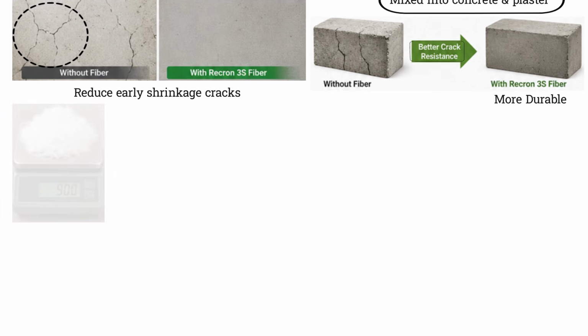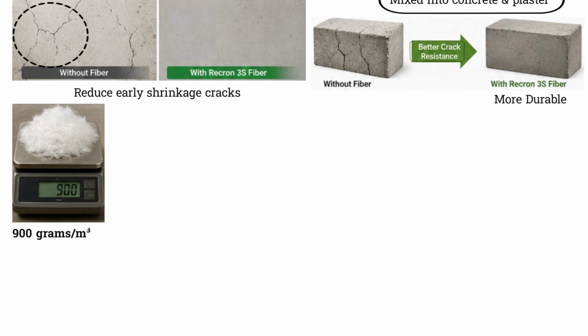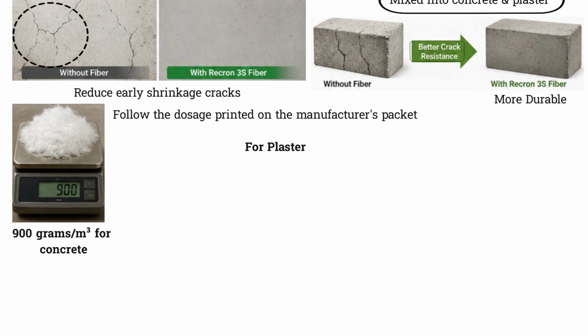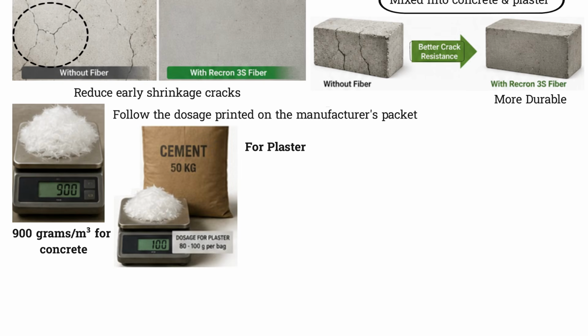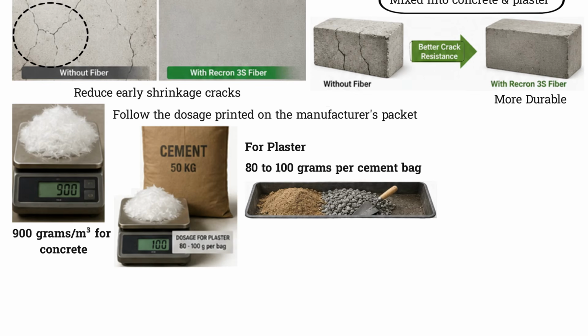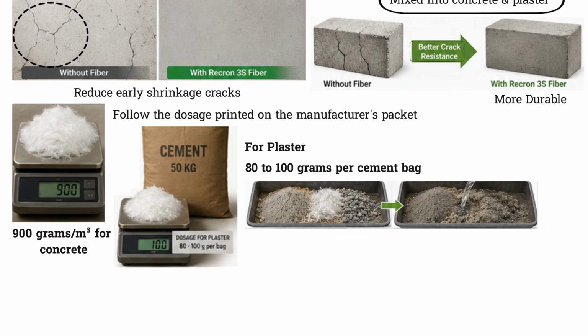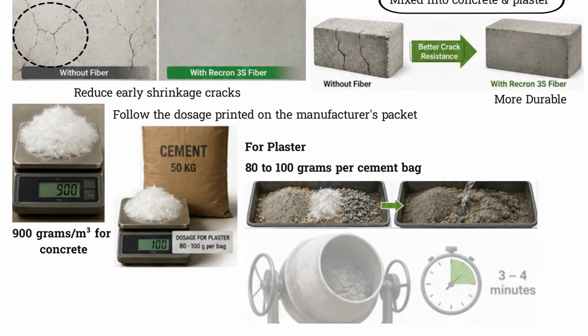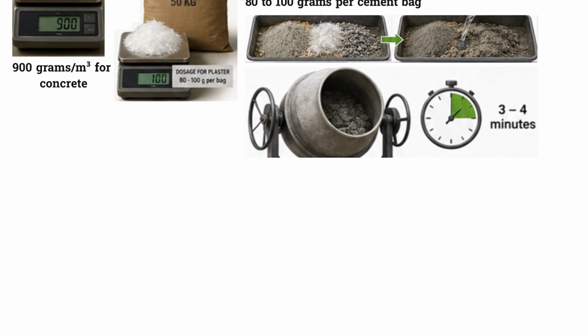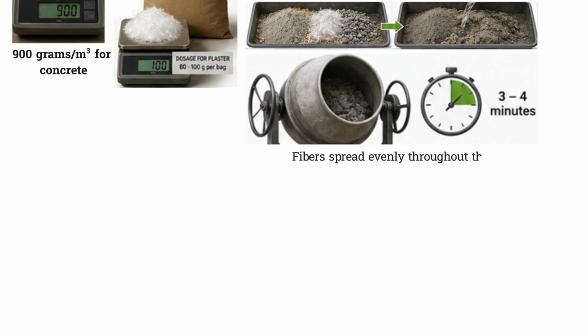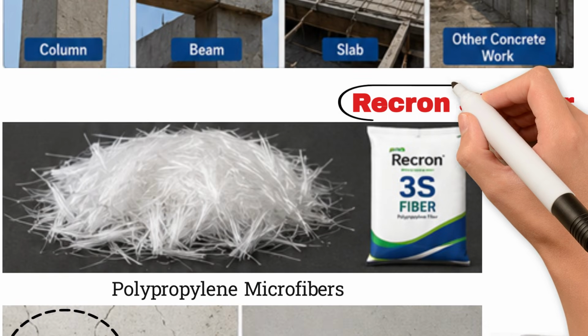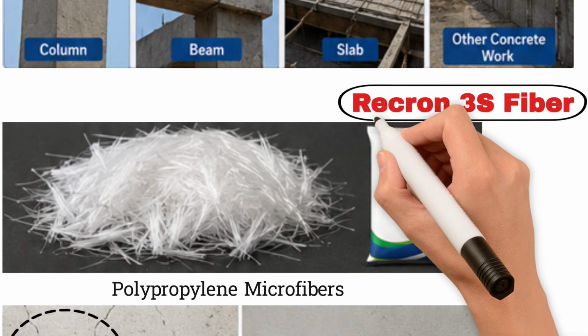For concrete, the typical dosage is around 900 grams per cubic meter of concrete, or simply follow the dosage printed on the manufacturer's packet. For plaster, many manufacturers recommend around 80 to 100 grams per cement bag. To mix it, first combine the sand and aggregate, then add the fiber. After that, add the cement followed by water. Mix everything thoroughly for about 3 to 4 minutes so the fibers spread evenly throughout the mix. If you want long-lasting concrete, this is one thing you should not skip.